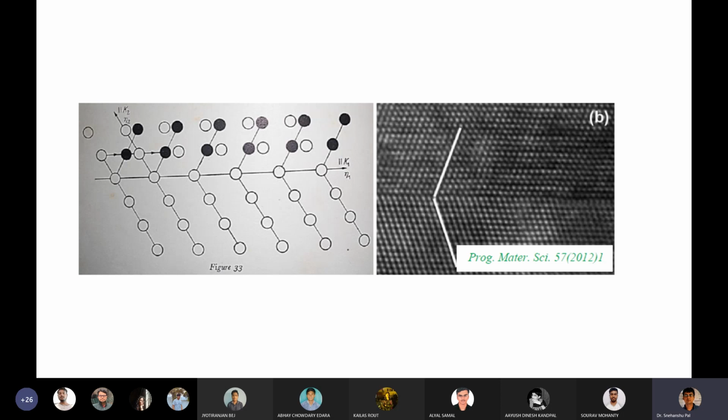Also you can see in the figure, stable twinning causes permanent deformation. That means the new atomic arrangement is also stable. So you have to find the energy versus lattice parameter. You see the derivatives, then there should be a local minimum. So you should remember that it is also a mechanism of plastic deformation. Now we have to accept the significance of twinning. This twinning phenomenon is also responsible for the plastic deformation process. It's a well accepted mechanism for plastic deformation.